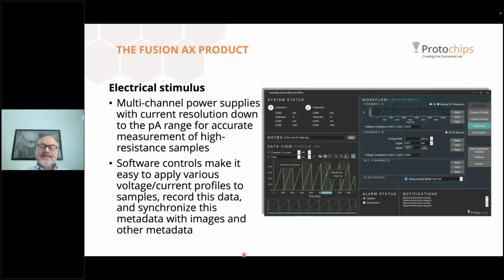Now, the electrical stimulus is provided by one or more power supplies with current resolution down to the picoamp scale. And this is important because by their nature, samples in the TEM are small and thin. And even really high current densities can still mean that you're measuring very low currents.